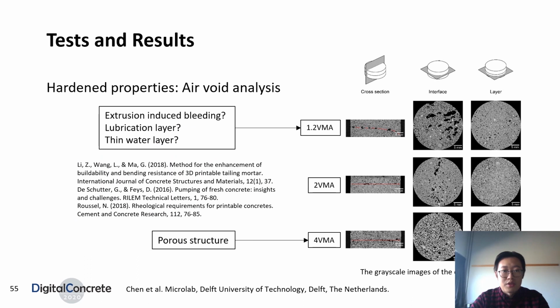But for sample 1.2 VMA, there are many coarse voids observed in the interface, which may be due to the extrusion-induced bleeding, the formation of a lubrication layer, or a thin water layer. However, it is still not clear. Further study is highly required.